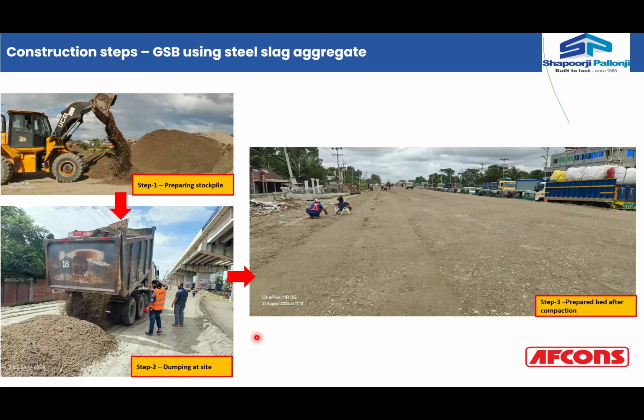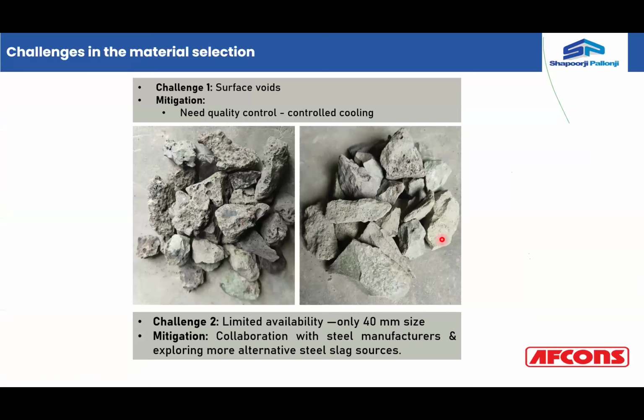Now, if you see the construction steps or the activities involved, you need to have a stockpile in place, which will be of the 40 mm slag, and then the material from the stockpile can be transported to the site using a dumper and dumped at site, and then you can do the grading and rolling operations to prepare the finished bed like this. This is a GSB bed, which is composed of steel slag aggregates.